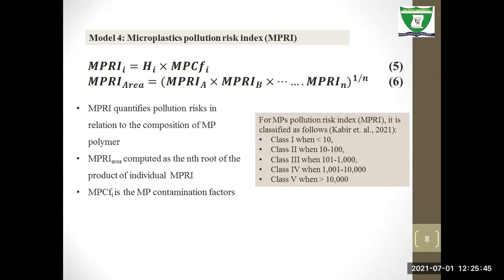Equation 5, which is the microplastic pollution risk index, is for a particular sample, while equation 6 is for the entire area. For the particular sample, you have the polymer risk index, HI, multiplied by the microplastic contamination factor. You calculate this for the different samples to get the microplastic pollution risk index. Now for the entire area, you take the microplastic pollution risk index for each sample, multiply them together, and take the nth root, which is based on the number of samples you are working with.